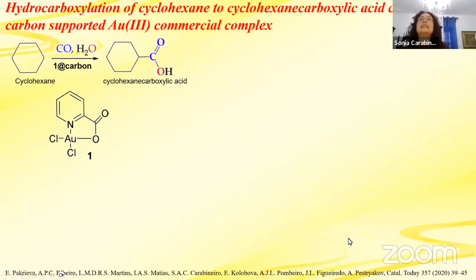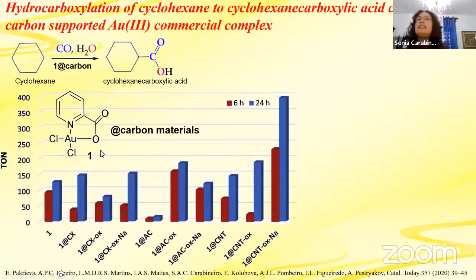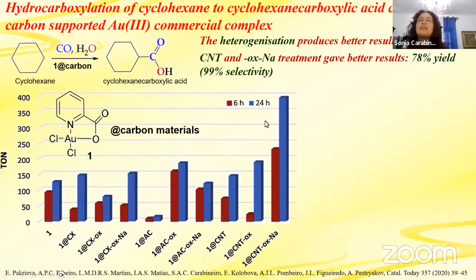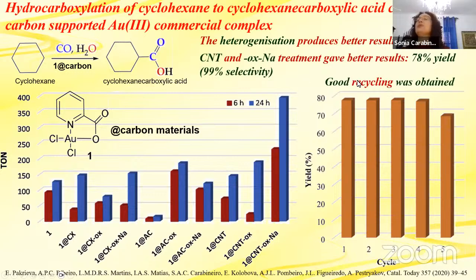We also tested this gold 3 commercial complex for this reaction, that is hydrocarboxylation of cyclohexane, to produce cyclohexane carboxylic acid. So this was the complex. And it was heterogenized on carbon materials. And again, we see the best result on carbon nanotube oxides. So best results, of course, heterogenizing, and again, with good recyclability. So it also works for this reaction.